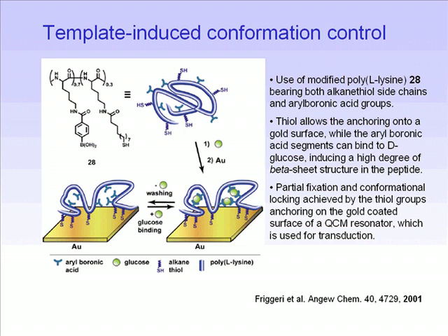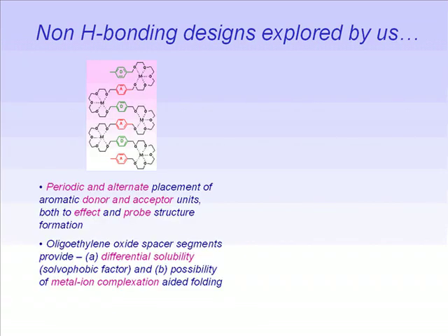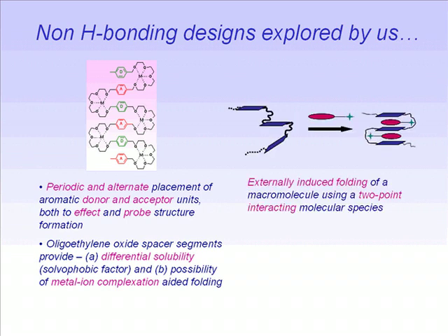Now, what this does is it fixes the conformation of this polymeric chain in such a fashion that it provides limited ability for these recognition units to move around. So once you pluck out the template, these units that can recognize this template are in the right disposition so as to pick up these kinds of molecules much more favorably over the ones that it's not imprinted for. In this example, it was glucose versus fructose.